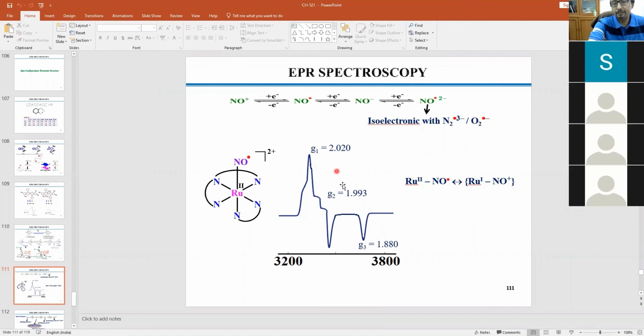And as a result, if you look at the g values, they are mostly ligand centered. That means NO-centered radical g values. But the slight anisotropy is reflected because of the 20% contribution of this electronic form. So these are very dicey. But you could reach a point via EPR and via spin density calculation where you feel quite comfortable, and people will accept your argument that this is how it is. So it is nothing straightforward that if you look at the EPR you can tell; you can make some guesses, but you have to give additional support through calculations. So in combination with calculation, EPR could be one of the very important aspects in realizing the electronic structural complications in such a class of molecules where both metal and ligand can participate in electron transfer processes. Okay.